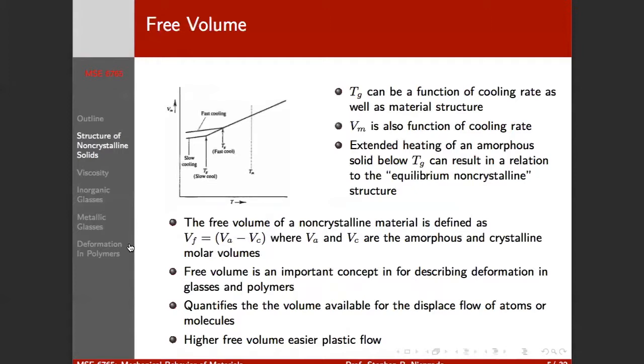But we can call this extra space free volume. And I think from a mechanical point of view, free volume is probably the most important concept for describing deformation in glasses and polymers. It's the idea that makes all of this make sense.